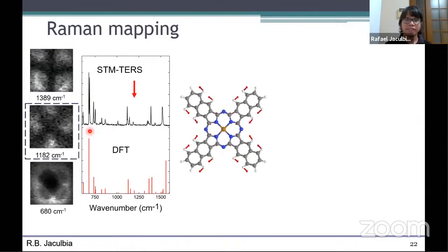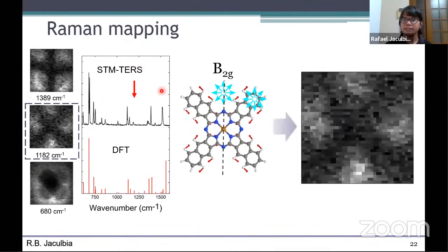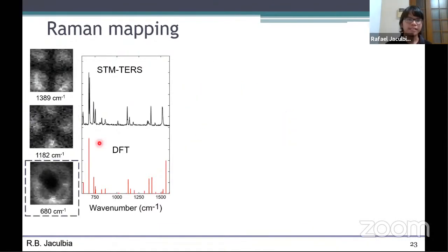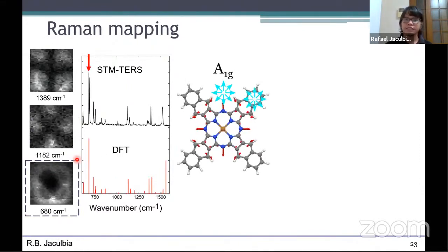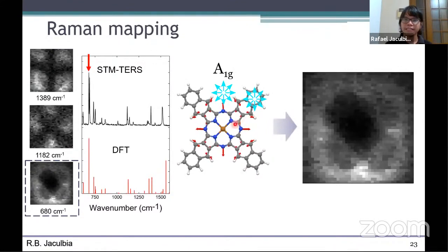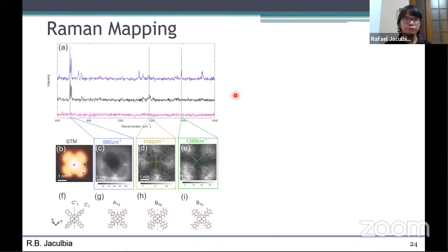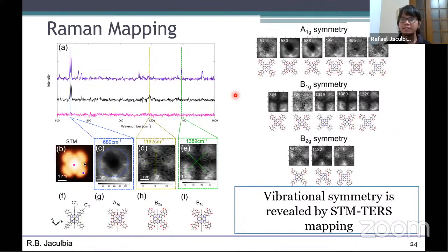It's the same for this mode. For example, this mode is like this, and the symmetry axis is like this. Again, when the tip is here, these modes are out of phase. And when the tip is here, the vibrations are in phase. Therefore, this should result in such a Raman pattern. And lastly, this mode showing a circular pattern, we found that this is the so-called A1g mode, which is basically a totally symmetric mode. So wherever you place the tip, there is a strong Raman signal, and that's why the pattern is like this. Therefore, we propose that the Raman maps we observe are defined by the symmetry. There are 3 different symmetries of this molecule we found, and the Raman maps show that it is sensitive to the vibrational symmetry.